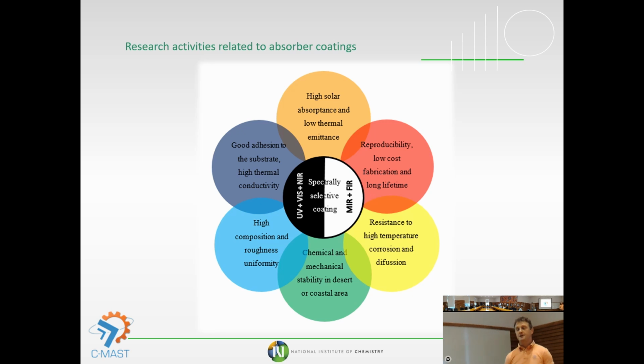Just because our contractor, BrightSource company, pushed us to the limit in order to fulfill all the demands. So the coating should have really high solar absorbance. Sometimes we didn't fulfill the demands of low thermal emittance. The cost of the coating was quite important. We should study the lifetime. We should study corrosion below and diffusion of elements, because when you are dealing with elements below from the substrate at 500 or 600 degrees, they diffuse inside the coating layer, influencing the crystal structure of the pigment, so the color is changing, so you absorb less light.